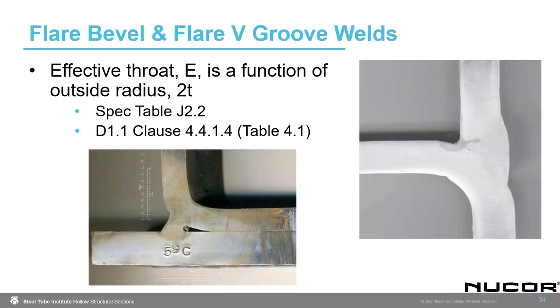Flare bevel and flare V-groove welds are very common in HSS because of that corner, if we're welding to the corner of a tube. We talked about those when we were talking about matched connections. The actual corner dimension, as I mentioned, was 2t on average, 2 times the thickness of the tube, but it's going to vary in size from mill to mill. Every HSS producer is likely going to have a slightly different corner radius. The effective throat is a function of that, though. It's given in the specification in Table J2.2 and in D1.1 also. This gap that you see in that picture on the bottom left at the weld root is common because we can't get the full penetration, and that's accounted for in the Z loss calculations.